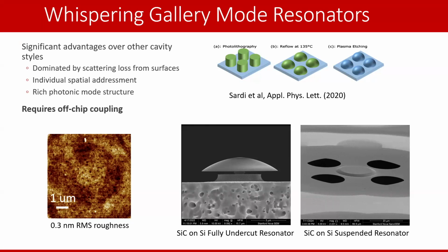So by simply defining circles in photolithography. First, sorry, let me take one step back: you can have an excellent surface finish on your silicon carbide on insulator platform by using chemical mechanical polishing on it first. So we can start with this 0.3 nanometer surface roughness on our silicon carbide, which is excellent. This prevents a large amount of scattering loss. And then we need to find a way to make sure that this transfers properly into the whispering gallery mode resonators when we fabricate them.